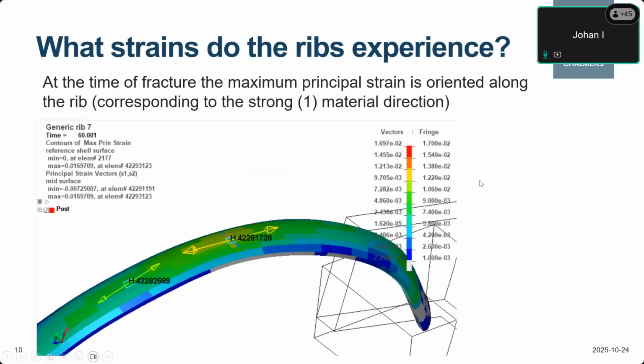So if we then look at the time for the fracture at the end of that simulation, we plot the maximum and the minimum principal strains as vector plots. We can see that the maximum principal strain is more or less aligned along the rib. And I didn't mention that, but if you look at the osteon direction in the rib, it's more or less aligned along the rib. So this means that we are actually loading the rib in tension here on the outside in the direction of the osteons.